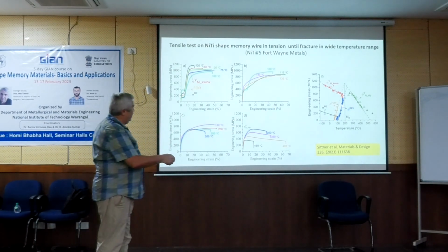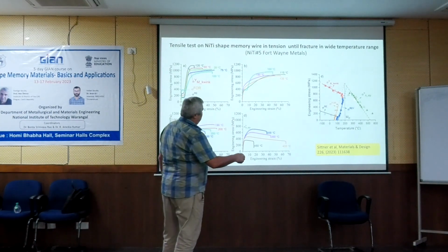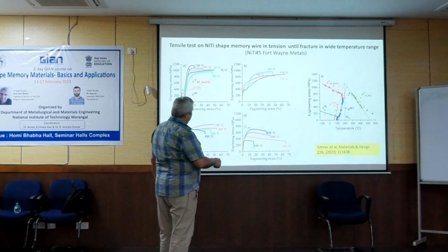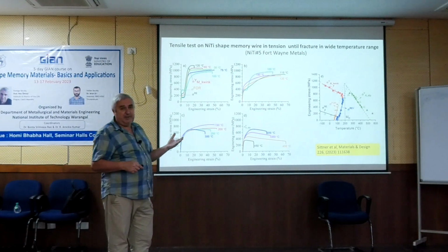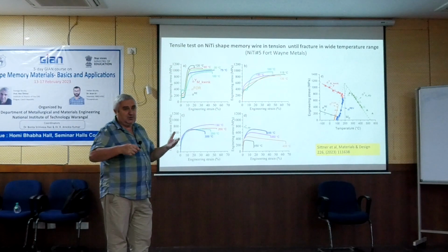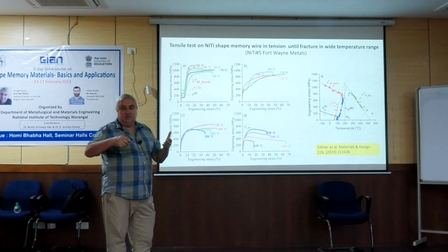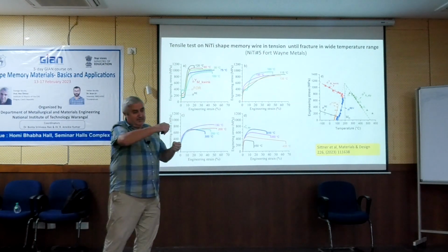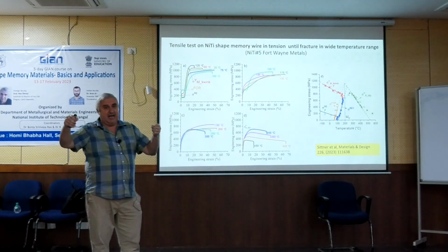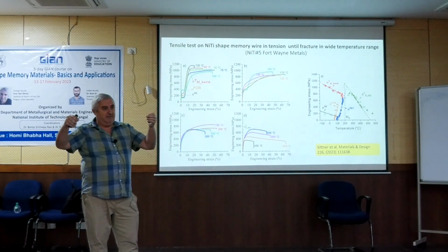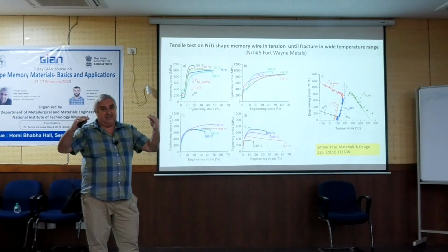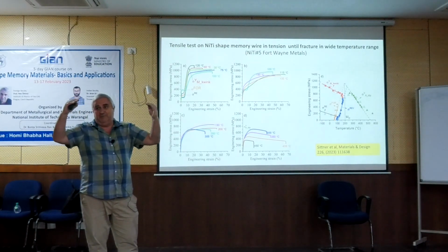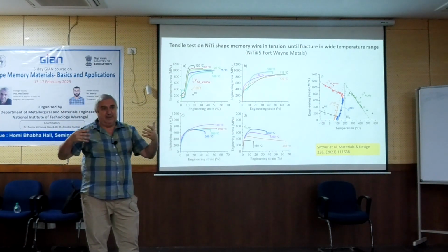No, because here the material deforms by dislocation slip, and dislocation slip is rate dependent. When she used the force control, it deformed very quickly, because she prescribed the same high force rate, and if you use a high strain rate or high force rate, the stresses are higher because of the strain rate dependence.